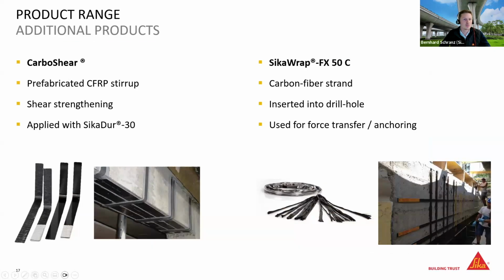What else is there? We also have prefabricated angles, which are post-installed anchors, stirrups, in case you have less shear capacity. And what we have been using for a long time is what we call the FX50. It's a carbon fiber strand that you can use for force transfer between all sorts of elements. So when you cannot have the rigidity of the angles or the plates or the fabrics, you can use this strand to create anchors, for instance, under the CFRP angles or under the fabrics, to really put the forces highly into the compressive zone or close the shear strengthening on top.